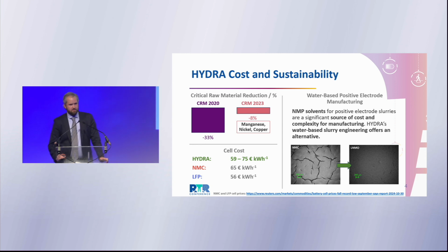And one of the big challenges in battery manufacturing has to do with the very first step when you start to make an electrode. The first step is you take your active material powder and you mix it together with a solvent to create a kind of paint-like consistency that you can then cast onto your foil. And while materials like graphite are stable in water, so you can do water-based solutions, many of the cathode materials are not. They start to corrode. And so most manufacturing processes use organic NMP-based solvents in their manufacturing.